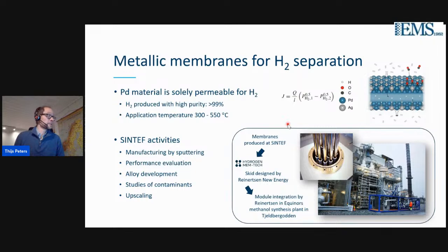The last membrane process that I myself have worked mostly on is high temperature metallic membranes for hydrogen separation. Palladium is a material that is capable of dissociating hydrogen on its surface, and then atoms are transported through it. In case the palladium itself is defect-free, you in principle can produce high purity hydrogen directly, up to 99.99%. This is also a high temperature membrane process, and it typically operates at temperatures between 300 and 600 degrees. Differently than many of the others, SINTEF produces membranes by magnetron sputtering.